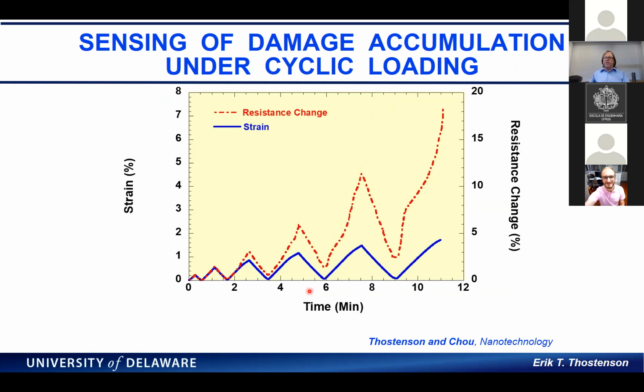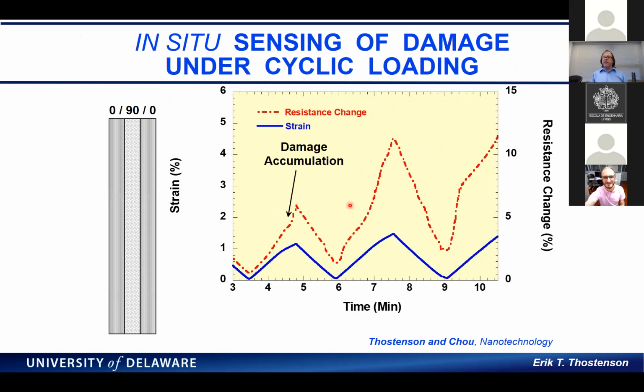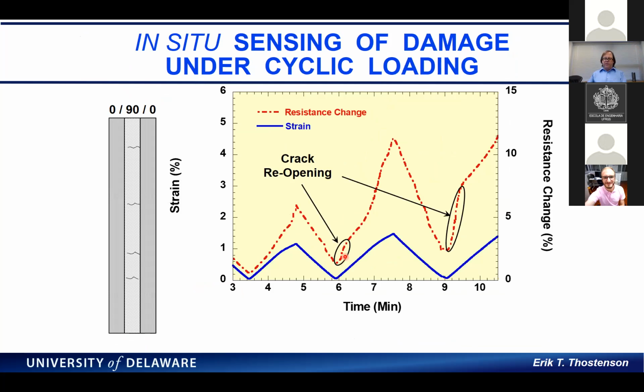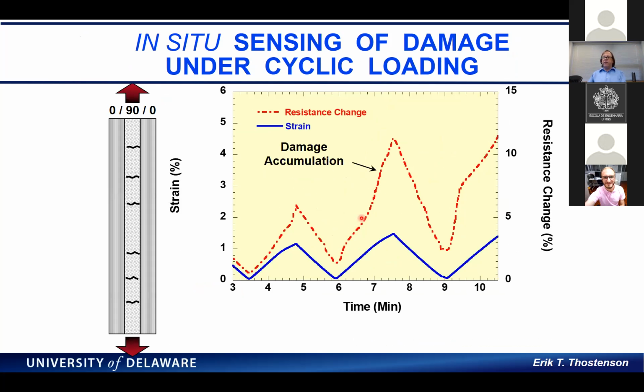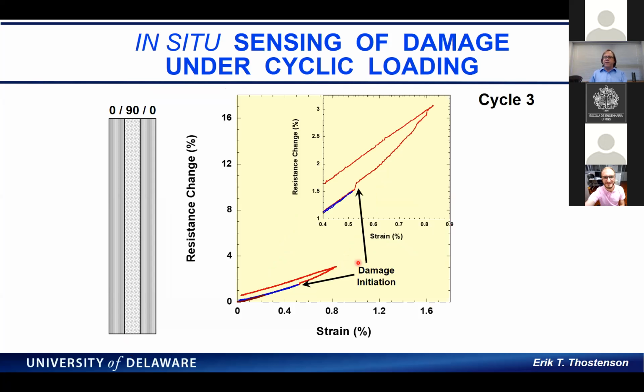And this really just shows the same thing. This is where we did progressive increasing cyclic loading, and at very low strain, you really don't see much, it's like a strain gauge, but then at higher strains, you start seeing that deviation, and it becomes quite nonlinear. So what's interesting is we see the crack reopening, then we see that elastic loading, and then we go to higher strain and we see new damage. And this was exciting in that we thought, well, now we can use this to detect a lot of other types of damage and do that in situ.